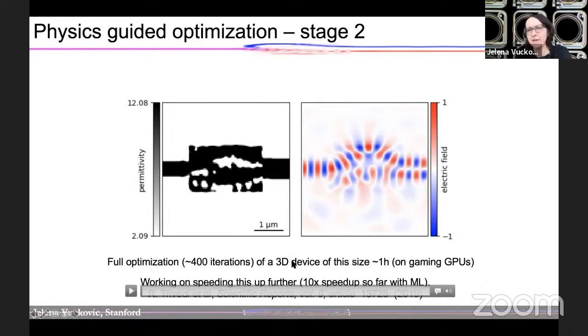And we spent a long time also developing fast electromagnetic solvers for this. So full optimization of something of this size would take about 1 hour on gaming GPUs. So we run it on gaming GPUs, not really scientific grade GPUs. And that would take around 400 iterations, which is on the order of about 1,000 electromagnetic simulations. And you can already see that this is faster than commercial electromagnetic solvers because you can run 1,000 successive simulations within an hour on kind of gaming platform.